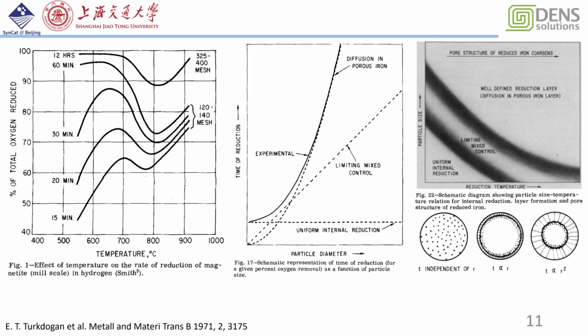Based on the experimental results, people suppose that at the different stages, several different mechanisms dominate. For example, at low temperature they call it the diffusion process, and at medium temperature people said there is a limiting mixed control mechanism. At high temperature, they have the uniform internal reduction process. However, people didn't give a very clear image of how the reduction happened in the different processes, under realistic reduction conditions and with high spatial resolution.